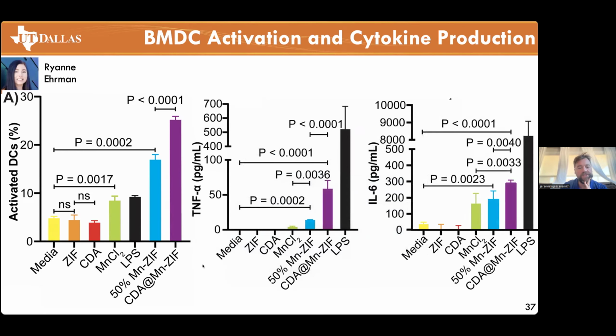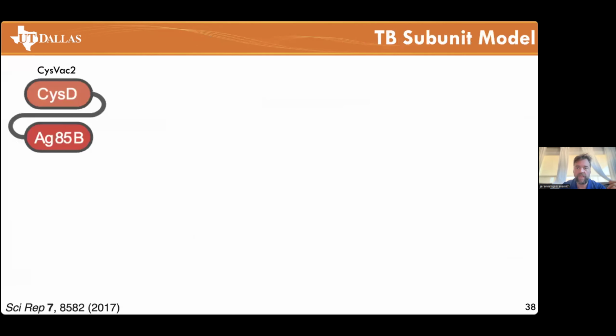Now, if we expand on this, I already showed you this activation of dendritic cells, we also have production of TNF alpha and IL-6. With these, essentially what we show is that we do have a production of these inflammatory cytokines, but not as much as lipopolysaccharide. If we had stuff like lipopolysaccharide, the pro-inflammatory cytokines would be so intense that they would make you extremely sick. And so we don't see that sort of large response, which is good, just in terms of safety. So we're going to activate the immune system.